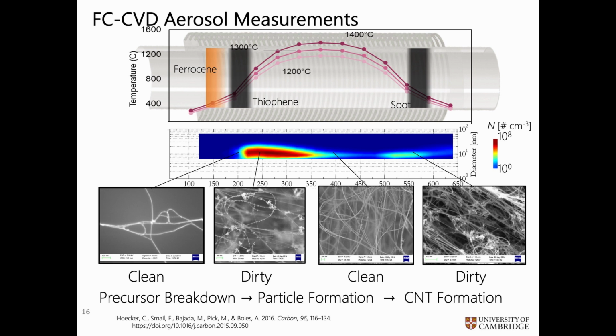So to look a little bit then at the catalysts themselves. These are iron particles in the gas phase, an aerosol, running down a reactor. And here's what a typical reactor looks like. It has a parabolic temperature profile. So if it's just a tube furnace, we are getting more sophisticated in the reactors, but this process basically started in tube furnaces. And basically you come in cold, you get very hot in the middle of a tube furnace, and then as the gases leave, they cool down again.